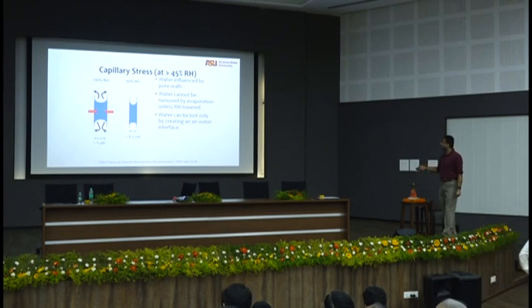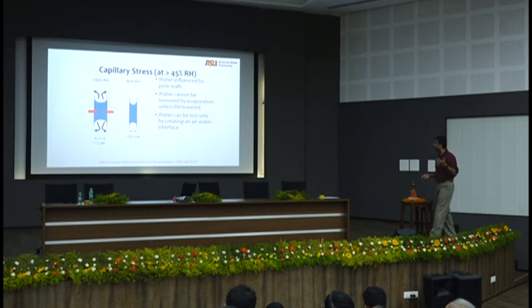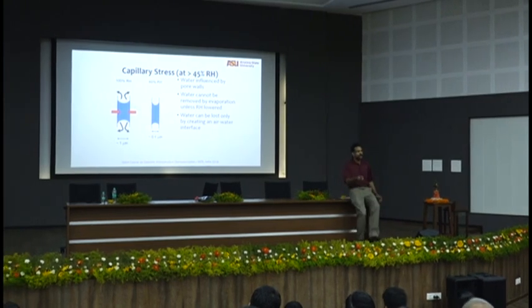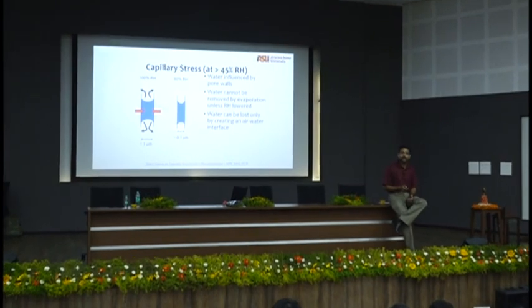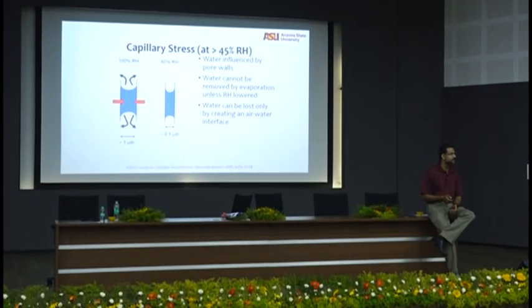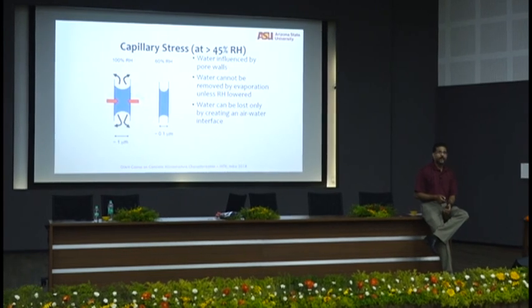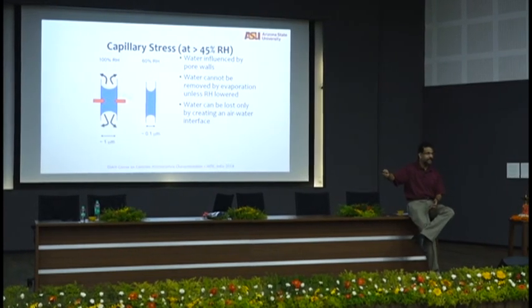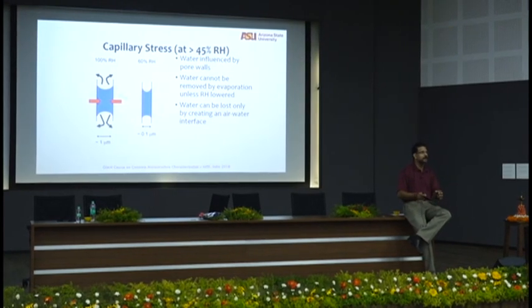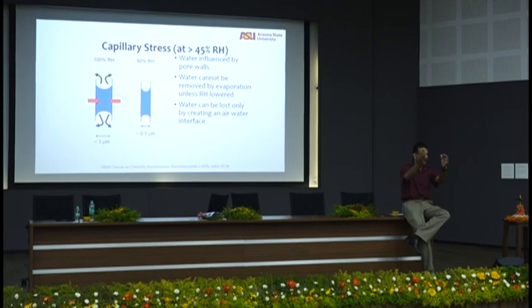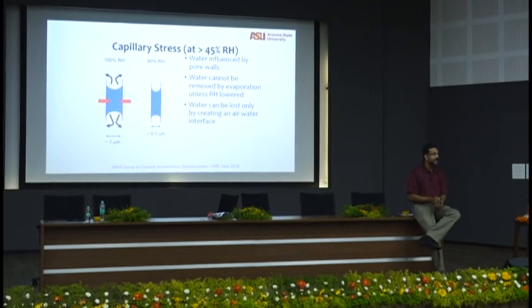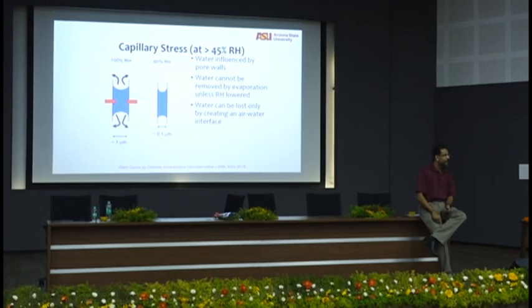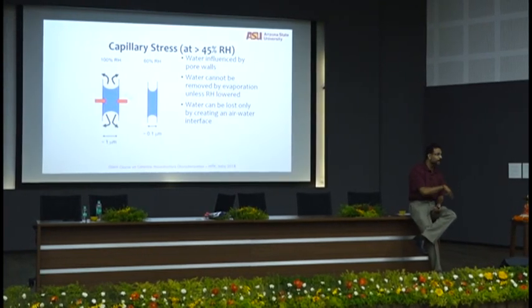Okay? So water can be lost only by creating an air-water interface. Water cannot be removed by evaporation unless RH is lowered. I gave you an example of your clothes drying, right? Water cannot be evaporated unless RH is lowered, which means when it is raining very heavily, its relative humidity is very high, you cannot put a cloth right next to the rain, it doesn't have to be in the rain, but right next to the rain in close relative humidity, and try to heat it up. It's not going to dry. What you need is not heat. What you need is removal of RH. If the heat removes RH, fair enough. Okay? So whatever mechanism that drops the RH is what you want.